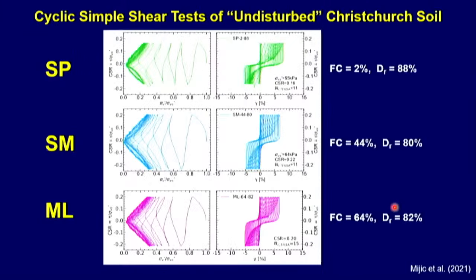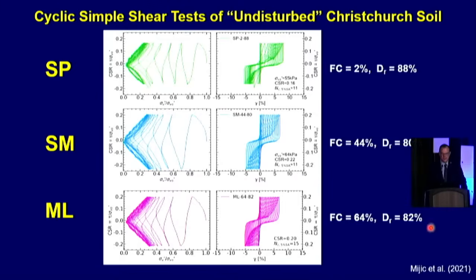Now, when we look at the testing, and this was the first simple shear testing done on undisturbed, retrieved Christchurch soils, clean sand, silty sand, low plasticity silt, all at the same relative density, plus or minus, their responses look very similar. This is the vertical effective stress decreasing as you cycle, and that's because of the increase in pore pressure. This is the stress-strain relationships.